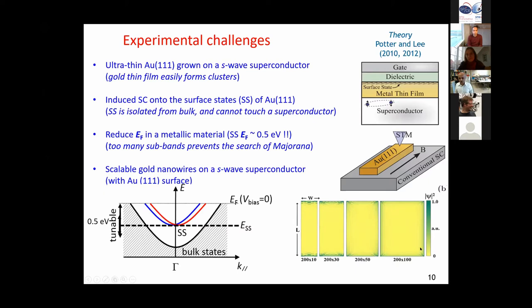Our program had to overcome several challenges: first grow epitaxial Au(111), second bring superconductivity to the surface state, third fabricate the nanowire, fourth bring the chemical potential down, and fifth ensure superconductivity survives when applying a magnetic field in addition to the exchange field. We started by finding the best way to grow vanadium and then gold on top so that very thin gold completely covers the surface instead of forming islands. We had to tune the growth conditions to achieve complete coverage with even two nanometer gold films.